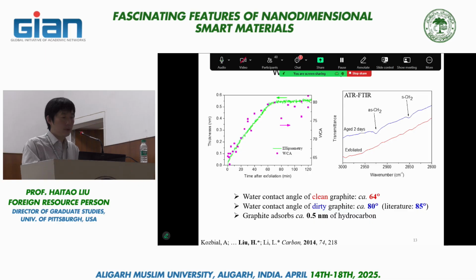All right, so based on this data, we again come to the conclusion that the wettability data of graphene and graphite that have been reported in the literature are terribly wrong. We know they're wrong because we can reproduce them, and all we need to do is to make the surface dirty to reproduce them. So with this in mind, we started to look at surface energy.